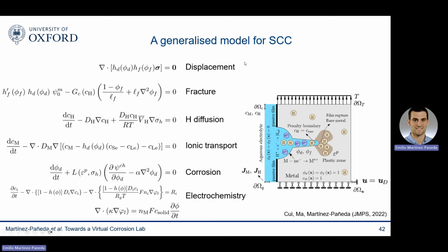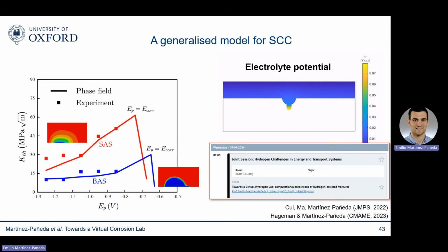And in this way, we can predict stress corrosion cracking for any choice of environment. And we can see the pit to crack transition and how changes in corrosion front geometry lead to different electrochemical behavior and hydrogen uptake conditions. And I discussed this more at length in the EUROCORR meeting through a talk that I gave. I was more focused on gaseous environments and on using this kind of mechanistic models to predict under which conditions we can transport hydrogen safely in natural gas pipeline infrastructure. This is a talk that also gained significant attention, so I decided also to record it and upload it in YouTube. You can find it somewhere in my channel.